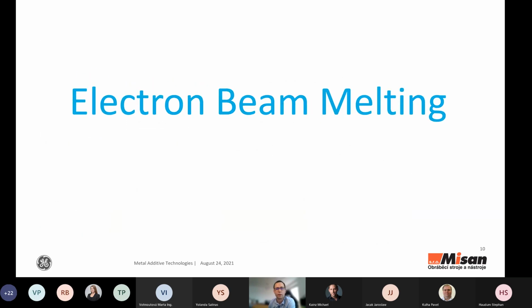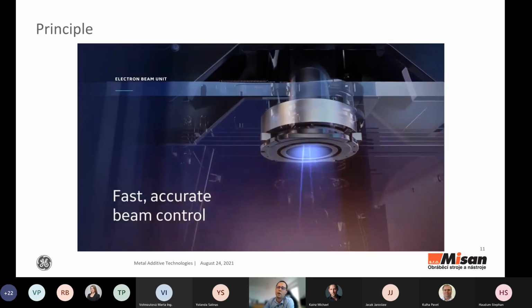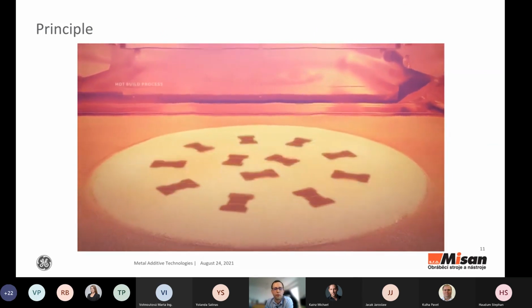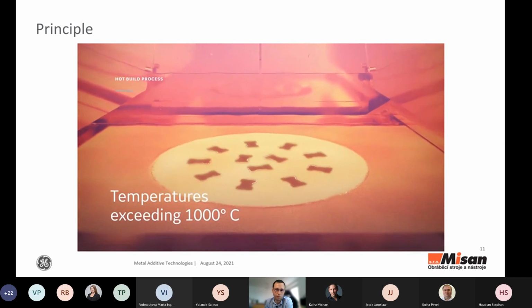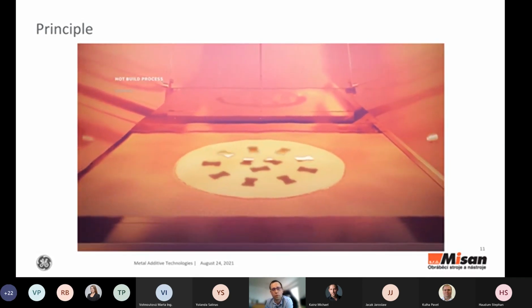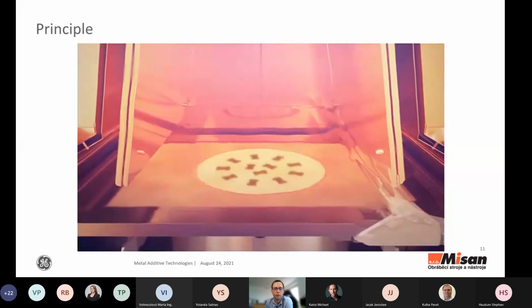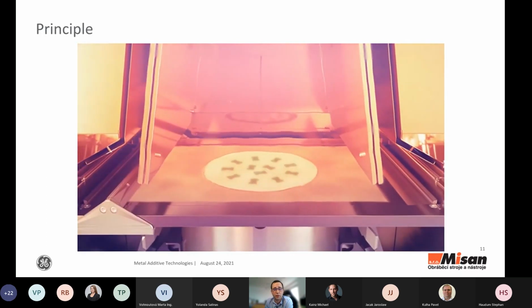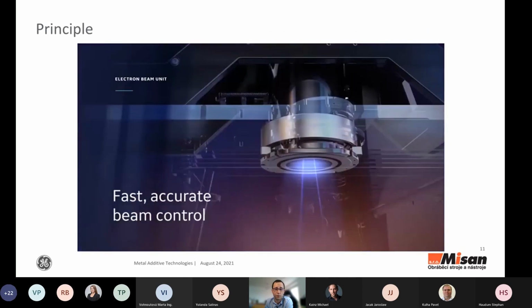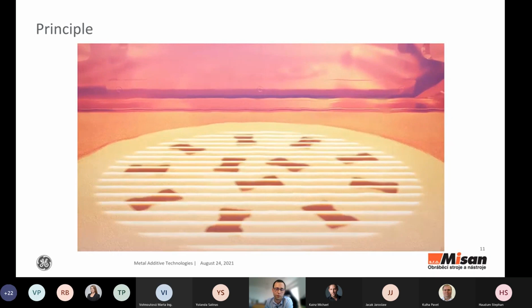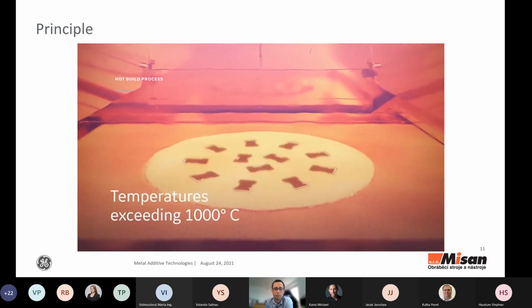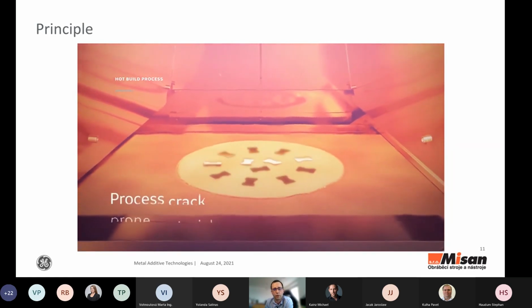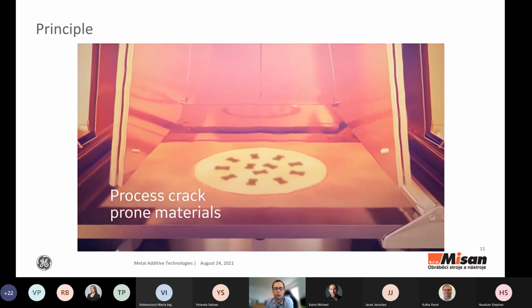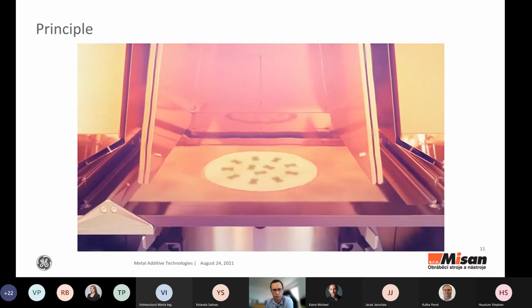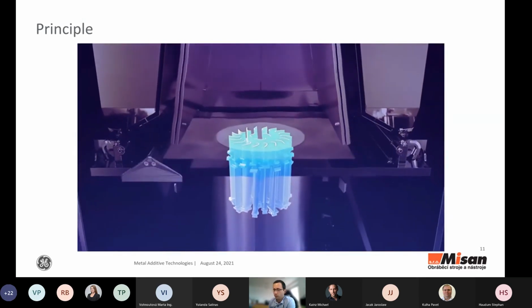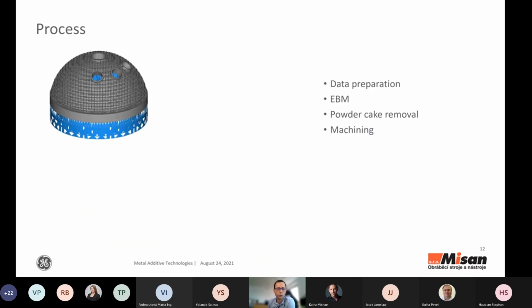Electron beam melting is the younger technology. It's more specific, but it has advantages. The main difference here is that it doesn't use a laser, but an electron beam emitter. So it uses electron beam energy to melt the metal powder layer, and it takes place in vacuum. So it's a hot process. Actually, you can keep really high temperatures in the chamber. It can exceed 1,000 degrees, and you have the possibility to stack parts one on top of the other. So that's a really big deal in aerospace and the medical sector. When you go for productivity, this is usually the way to go.